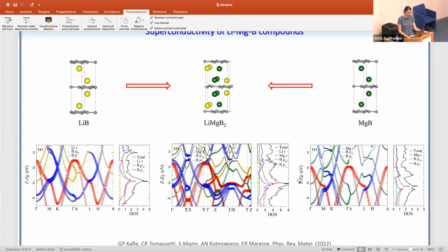Here I'm showing the band structure of these two compounds. Compared to lithium boron, in magnesium diboride the interlayer band, the NFE band, is slightly shifted up, because now the interlayer distance has increased, and there is more space for the electrons to occupy these states, which are in this free interlayer region. On the other hand, the sigma bands are still wholly occupied, and more importantly, right now we have density of states coming from the boron pi states. So we can see, both in lithium MgB2 and in magnesium diboride, there is a significant contribution that comes from the boron pi states.